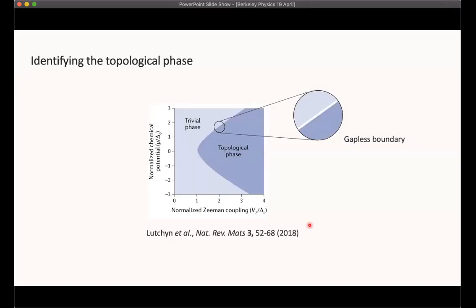So let me return to that phase diagram. As I said before, there's a trivial phase. It's where every Majorana is paired with its neighbor on one of these sites in the Kitaev chain. There's a topological phase where we expect unpaired Majoranas at each end of the wire. And crucially, along this boundary between the two phases, along this topological phase transition, we actually expect that the system is gapless, that the entire chain is gapless. And so observing a gapless boundary is going to be a very useful waypoint on this map to help us understand where we are in phase space.